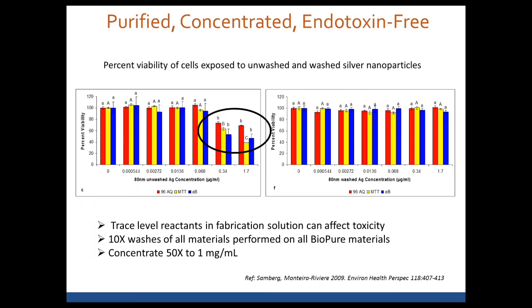So the benefit of the SBIR was that we were able to really provide materials and then interact with the toxicologists. Some of the early experiments, this was some work done by Nancy Monteiro-Riviere, where we had provided them some materials, they had seen some toxicity, we had tried to tease out what the reason for that was, and it turned out that there were some residual reactants in that initial solution, and once we purified it, that toxicity went away. So that was very early on and really emphasized the importance of purifying.